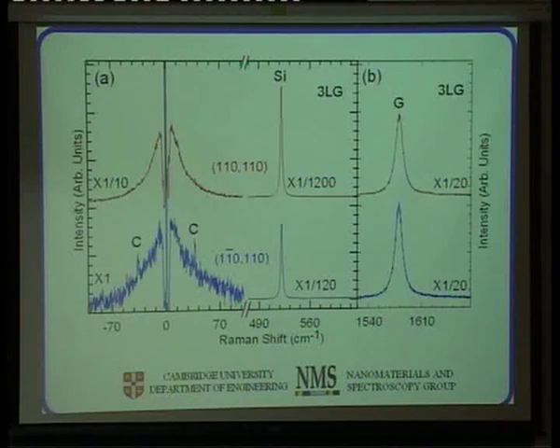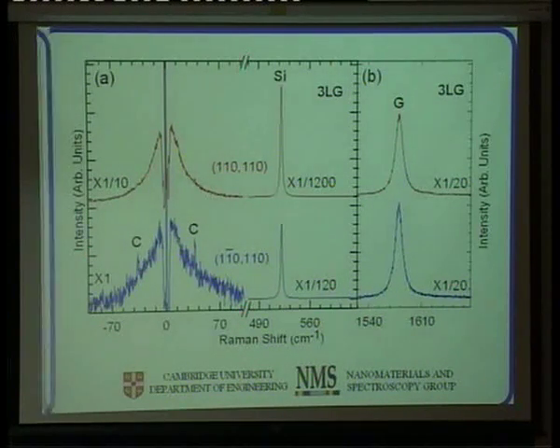We call this the C peak, because it's related to the interlayer coupling. It turns out that you can suppress this electronic scattering from the silicon dopants by changing the polarization. And so if you do polarized Raman measurements in graphite, you can start seeing it.